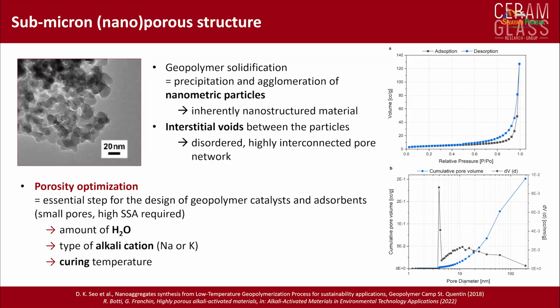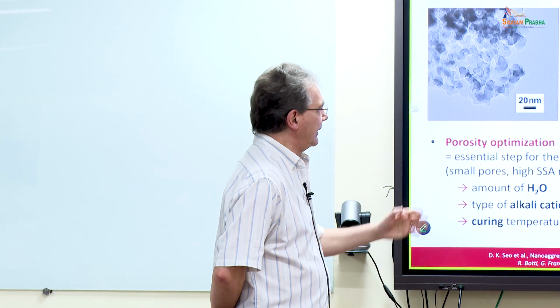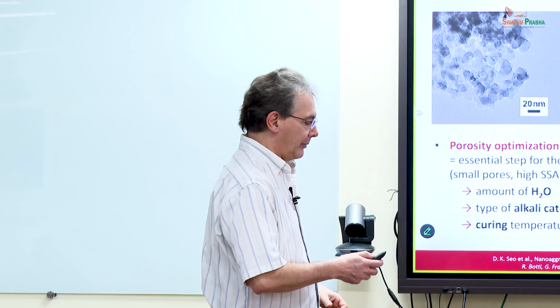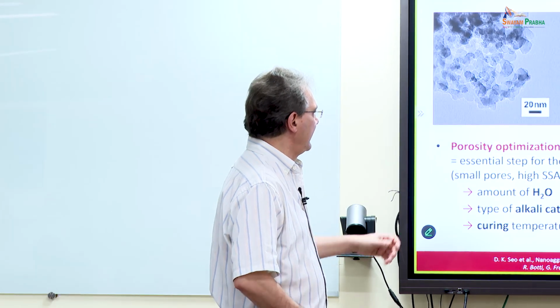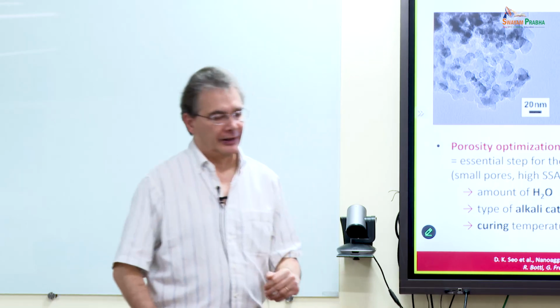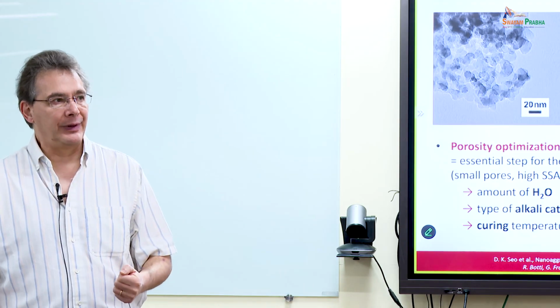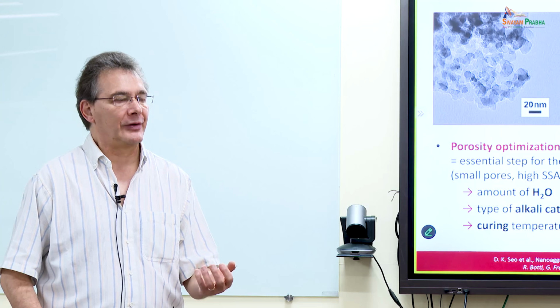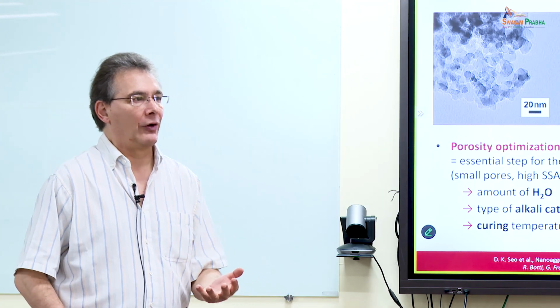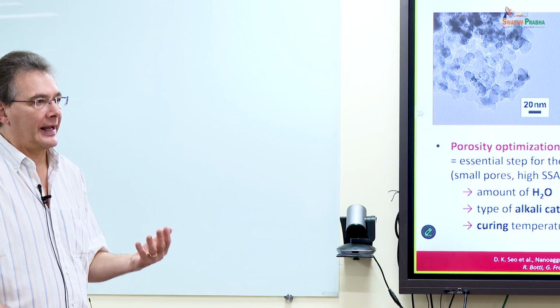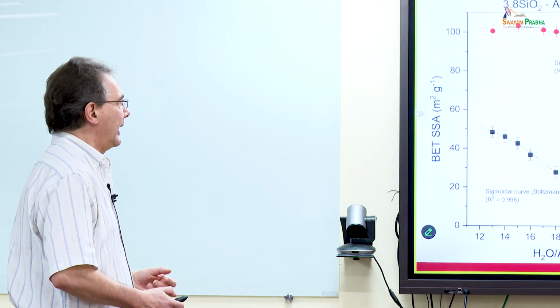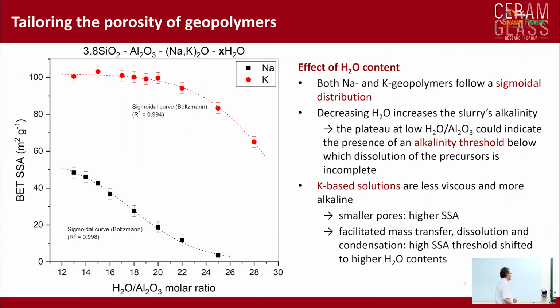I mentioned that due to the way the gel structure is created, it is based on nanometric particles, and between the particles that are bound chemically together, there is porosity, typically mesoporosity rather than microporosity. And it is interesting to see that the volume and the size of the pores can be modified by changing the amount of water that you have in your system, or the type of alkali cations and the curing temperature. So there are different ways in which you can affect the specific surface area.